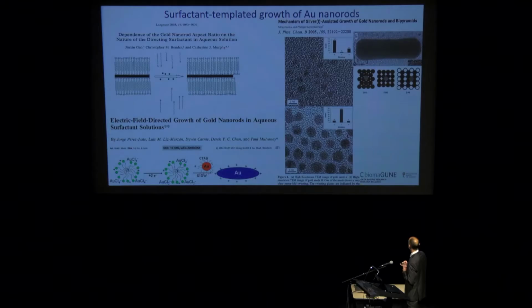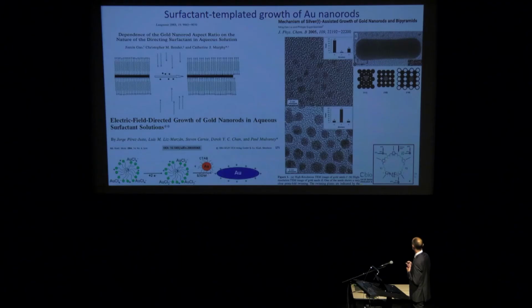And so the type of nanorods that you obtain from single crystal seeds and from pentatwin seeds look similar, but they are not the same. So the ones you grow from the single crystalline seeds are also single crystalline, most of them. The ones which grow from the pentatwin seeds actually form either bipyramids or pentatwin nanorods. And this is quite interesting, and it also opens up plenty of questions and parameters to be investigated.